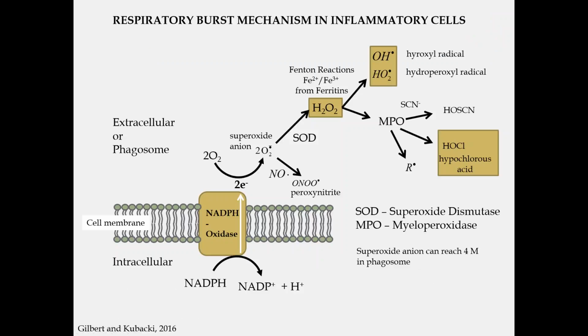Now, I want to finally move to this respiratory burst effect, this idea that cells can generate conditions that might exacerbate corrosion. So inflammatory cells engage in respiratory burst, and what will happen is a phagocytic cell will take oxygen, and through this NADPH oxidase molecule in the cell membrane, simultaneously oxidize NADPH and reduce oxygen to a superoxide anion. This superoxide can then undergo various transitions that are shown here, and in particular I want to focus on hydrogen peroxide, hydroxyl radicals, and hypochlorous acid.